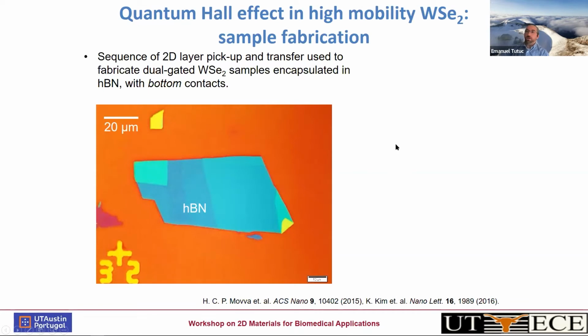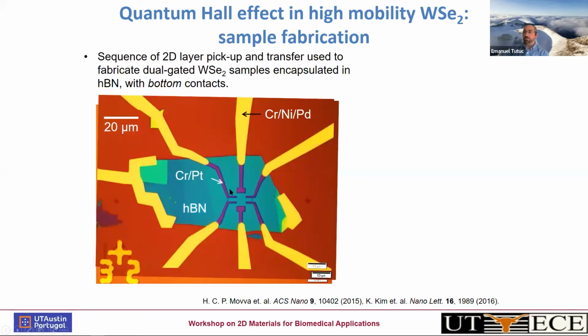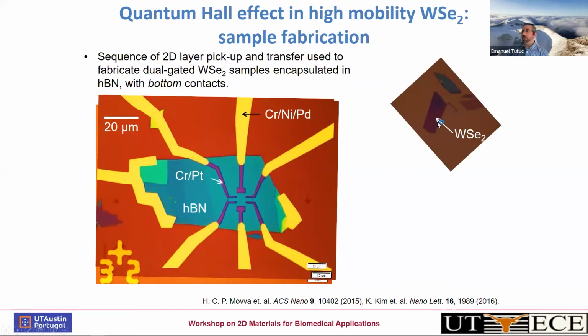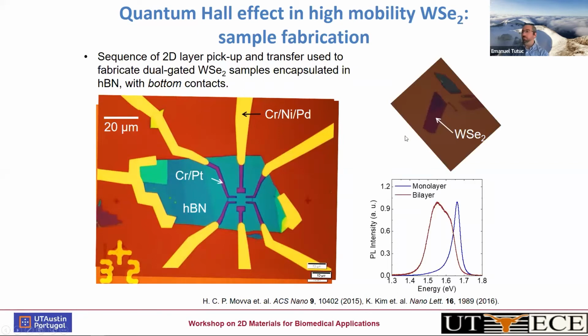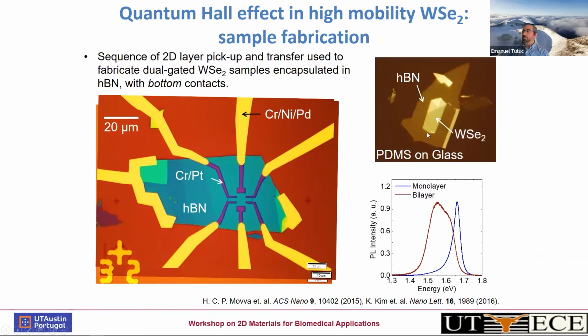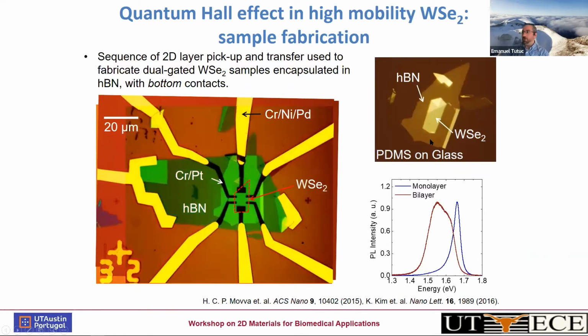So let's look at the actual device. I'm going to show the tungsten diselenide encapsulated in hexagonal boron nitride. So we'll start with hexagonal boron nitride, which is going to be a substrate, and we're going to pattern the contacts first. This is a device design that enables lower contact resistance, particularly for transition metal dichalcogenides. So this is the bottom substrate with the contacts, and then we exfoliate tungsten diselenide. We do PL or Raman, just like Xintong described earlier. And then if we're satisfied that the flake has the requisite quality, we pick it up with a top dielectric of hexagonal boron nitride, and then land it onto the bottom contacts shown here.